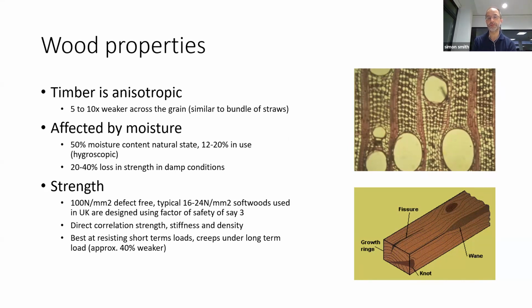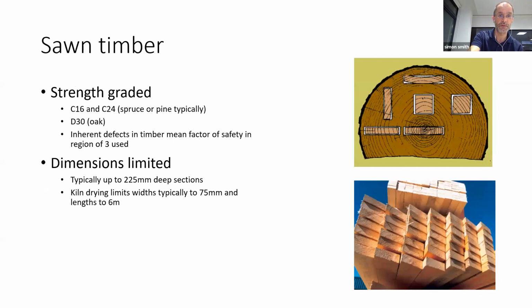But typically we use materials anything from C16 to C24 for softwoods, and we typically design with a factor of safety of probably around 3 or 4. It's not that straightforward, but very typically. There's a direct correlation between strength, stiffness, and density. So the heavier a piece of wood, the stronger and stiffer it tends to be. And wood is very good at resisting short-term loads, but it does creep under long-term sustained loads. So it's not an easy material to design with as a structural engineer, I must admit.